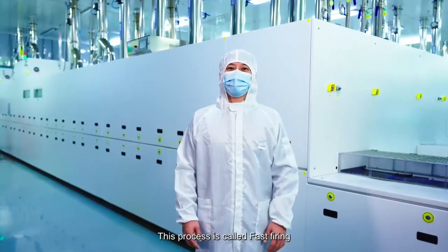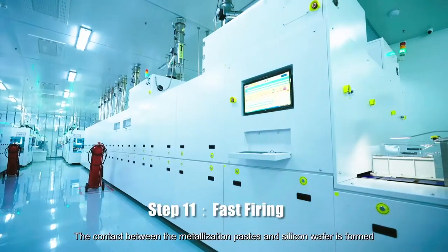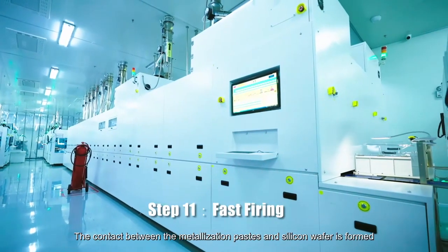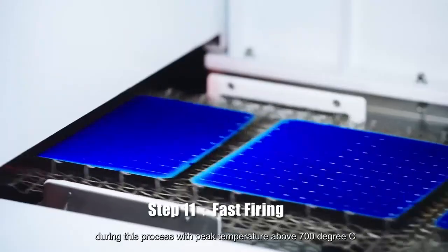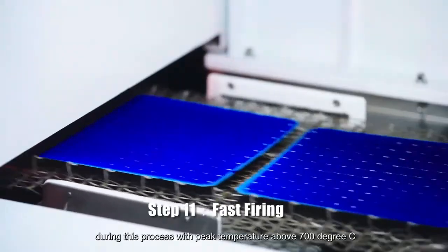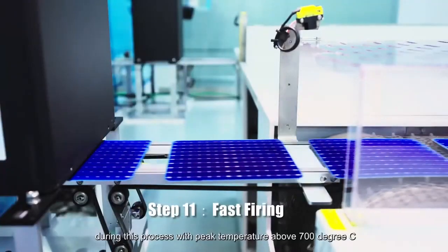This process is called fast firing. The contact between the metallization paste and silicon wafer is formed during this process with peak temperature above 700 degrees C.